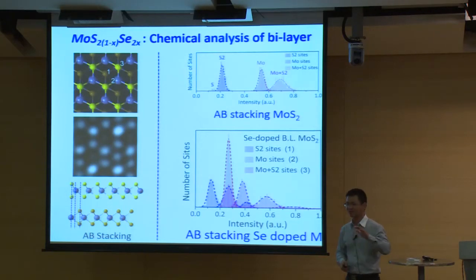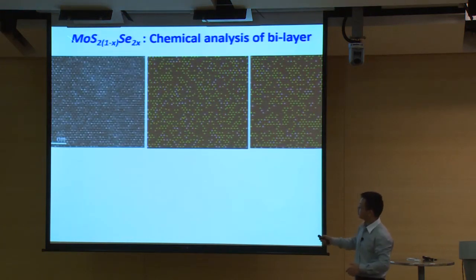Okay, for the bilayer case, it's maybe more complicated. So for most of the bilayers, we've been seeing the TEM is AB stacking. So we can still do the same thing. We can get the AB stacking, the intensity mapping of the pure moly disulfide looks like this. And after doping the selenium into this system, we can get a lot of peaks here. And resolving these peaks, we can translate the bilayer selenium doped moly disulfide to each layer. And currently we can't tell which is the top layer and which is the bottom layer, but we can tell the composition of each layer.